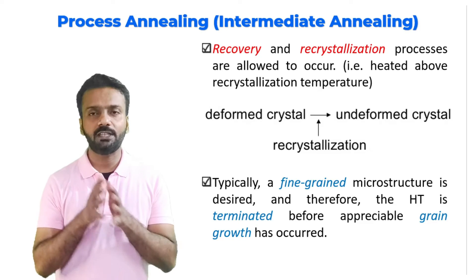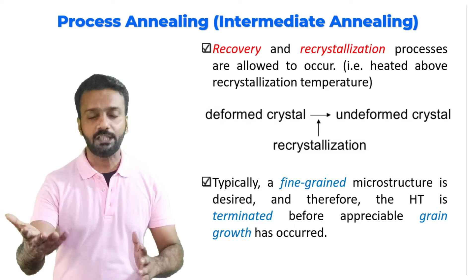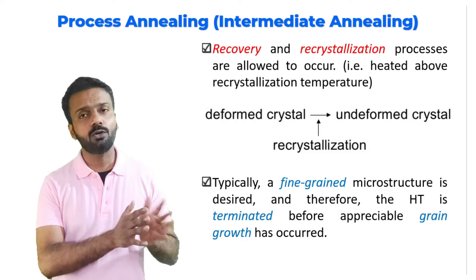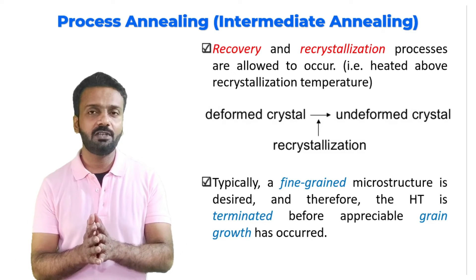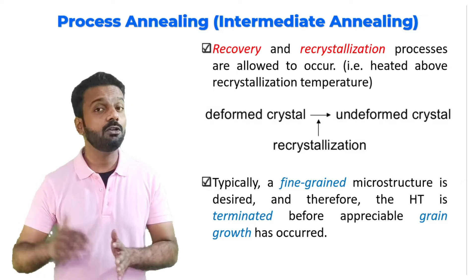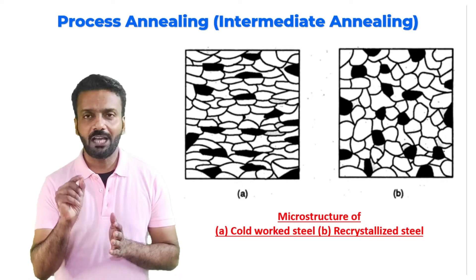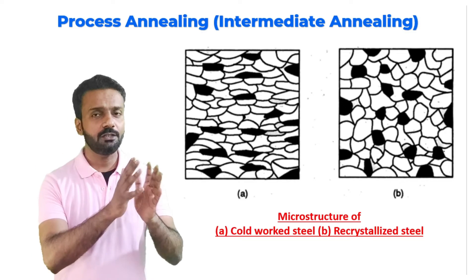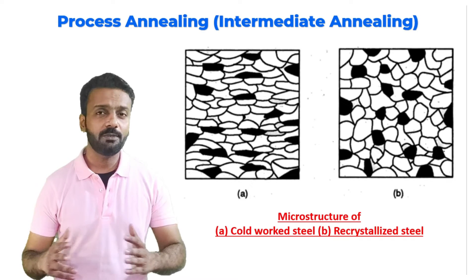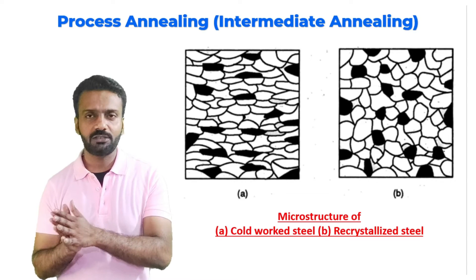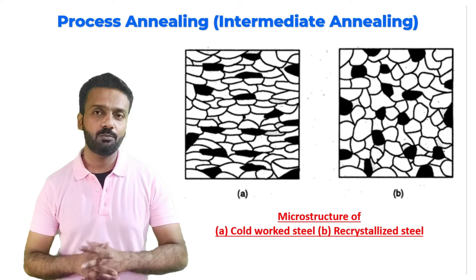There is a cycle of deformed grains, recrystallization, then deformation again. We must ensure we don't supply too much heat and cause grain growth — we just go to the temperature where recrystallization of the grains occurs, not grain growth. Here is an example of cold worked steel where grains become elongated, making further deformation difficult. After process annealing, the grains are equiaxed and more pliable, allowing further plastic deformation.